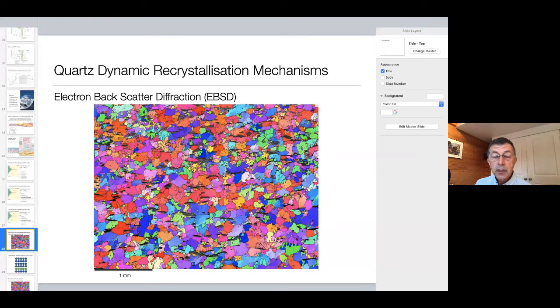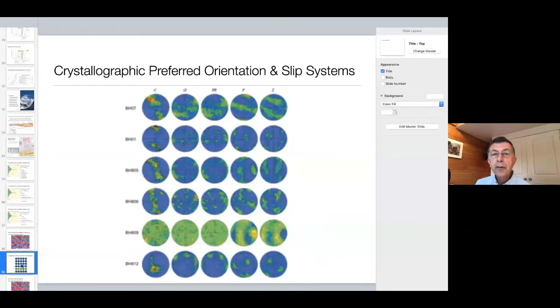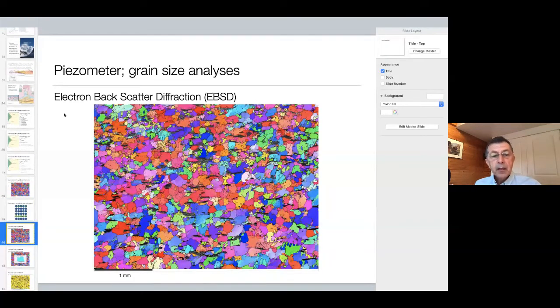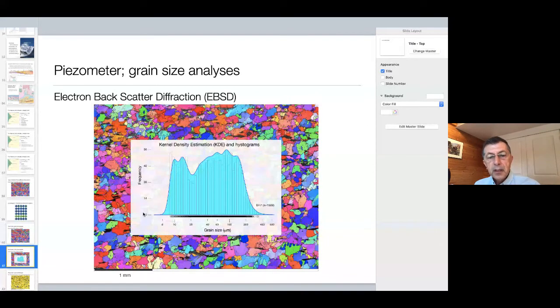We can use this data, plotted here in a map view, to also calculate the crystallographic preferred orientation diagrams. Here are the samples along the cross section and different crystallographic directions, but I'll not go into these details today. I briefly mention that the patterns of distribution of different crystallographic axes allow us to determine the slip systems, which are a function of the temperature but also strain rate. So going back to this image, EBSD imaging allows us to recognize the grains, and when we analyze the grain size from this image, this is the distribution of the grain sizes in microns. So there's a mean grain size.